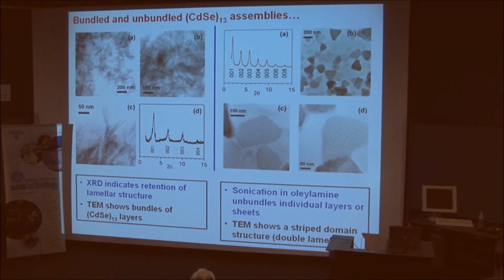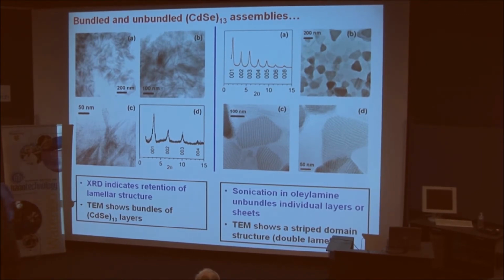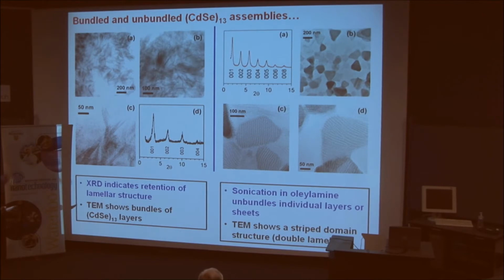And we can sonicate these bundles in a long-chain oleylamine solvent mixture. And the bundles start to come apart. Individual layers start to unpeel from these bundles. And here are the images of those individual layers. And if you look closely, you'll see that they have a striped domain structure.